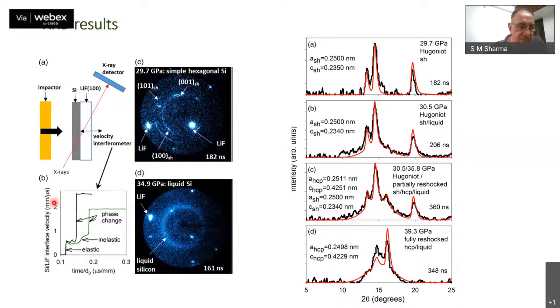You see here typical particle velocity curves recorded in these experiments. For example, this is the elastic jump, and then there is an inelastic, and then this is the phase change indication, which is taken at the final steady value, representative of the velocity and stress it attains.